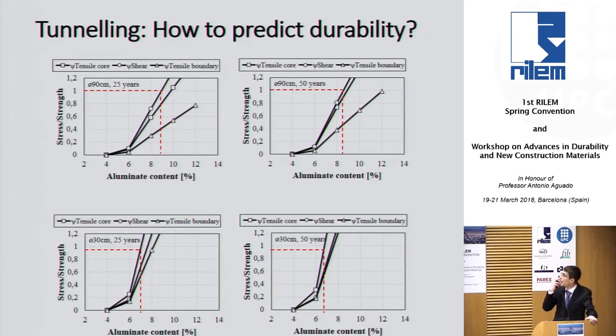So here you see some results on the influence of the aluminate content of cement on the stress strength ratio. So one means that we are going to have cracks. So you see that different contents of aluminate in our cement, if you increase the content of aluminate, increase the risk of damages, right? So we can predict it. And interestingly, we found that the 5% that we commonly use is a good threshold in most cases, although it might vary depending on the size of the element. So here you have a variation in terms of size, like 90 centimeter thickness, 30 centimeter thickness, and you see that the threshold above which the likelihood of damage increases is moving.